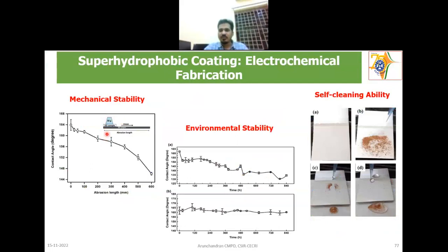And then if you develop this kind of coating, we should find out the mechanical stability. What we did is we rubbed the surface using silicon carbide paper with a 50 gram load. This is a standard test we use for these kinds of coatings. We found that as the abrasion length increases, the contact angle value decreases, but it is still in the hydrophobic range. For environmental stability, we monitored the contact angle for almost 1 month in NaCl solution, and it keeps decreasing, but it's still in the hydrophobic regime. The ambient air UV stability is very good up to 1 month. And then the self-cleaning ability: we keep some dust here, then the water is dropped here, it rolls off, and while rolling off it carries all the dust with it and removes it.